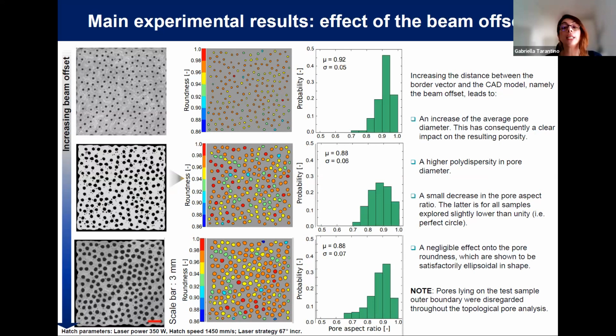Now, taking the same numerical model, if we just change what we call the beam offset, basically the distance between the contour parameter and the STL outer edge, we can see that the same numerical model can be printed with huge differences. And we quantify those differences via image post-processing. We can see, first of all, that mono-size pores cannot be printed. Essentially, the microstructure contains pores which are polydispersed in size. They are designed as perfect circles, but in reality they have an elliptical shape with the aspect ratio diminishing with increasing this parameter, the beam offset, but they remain of pretty good round shape.